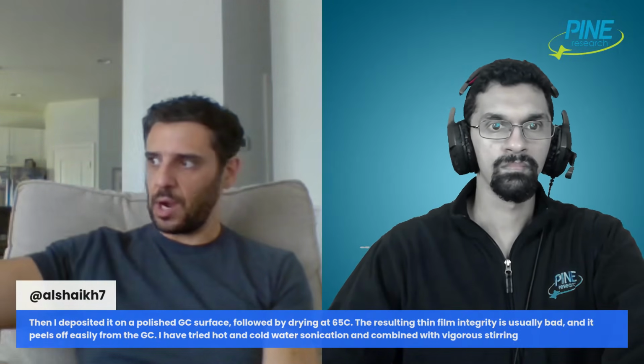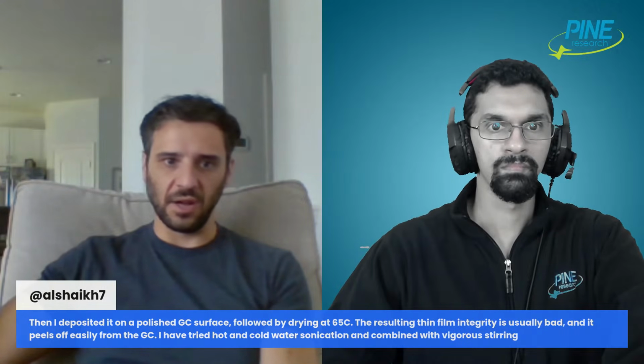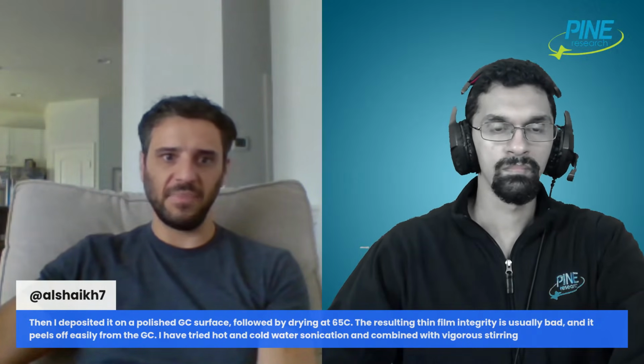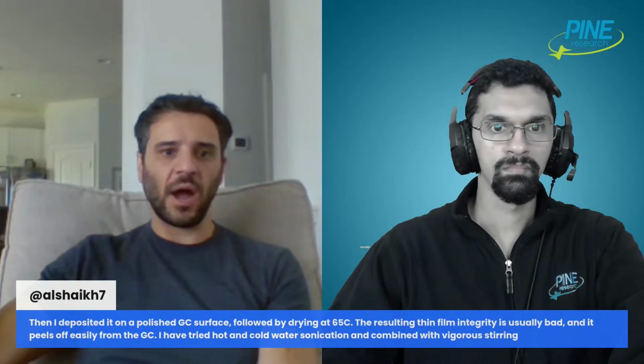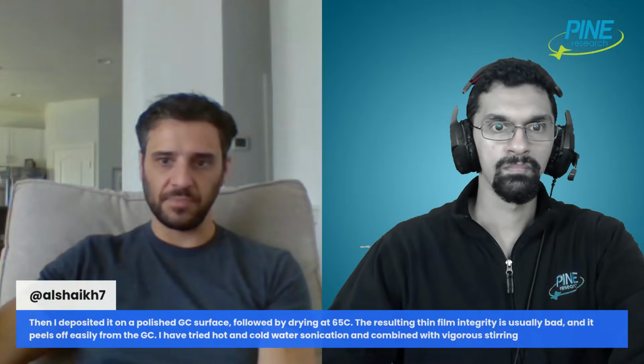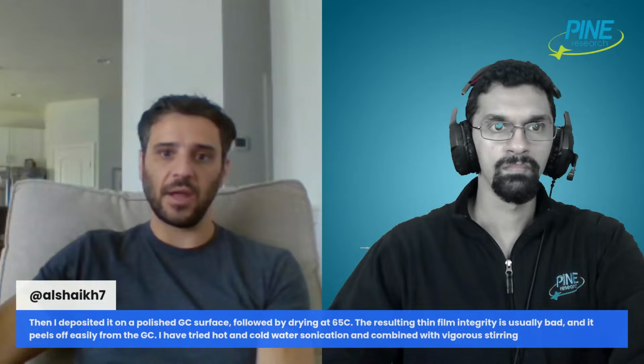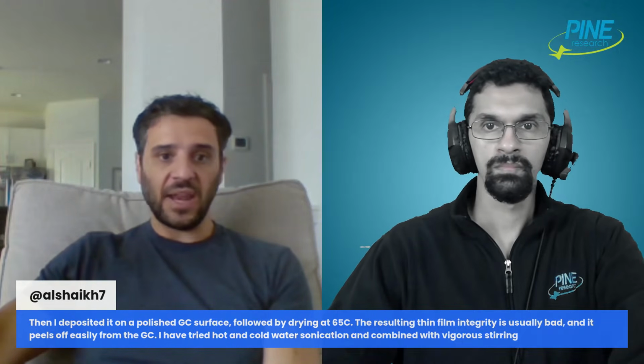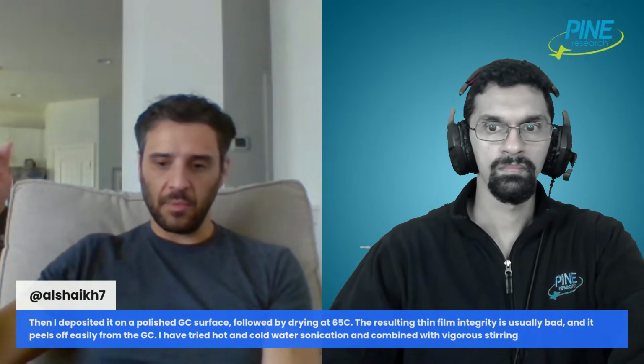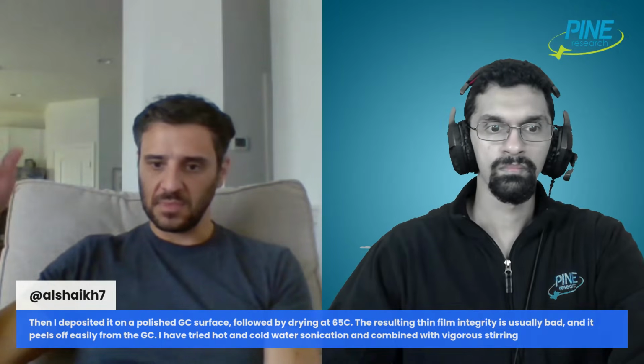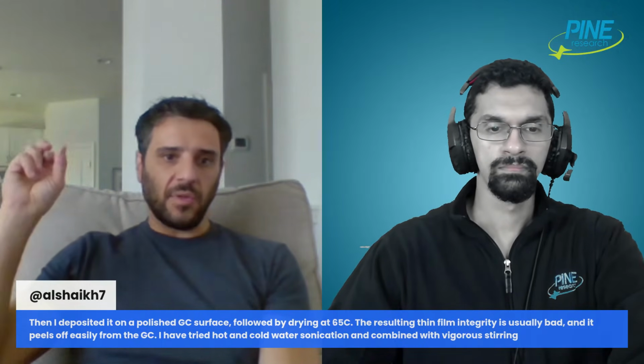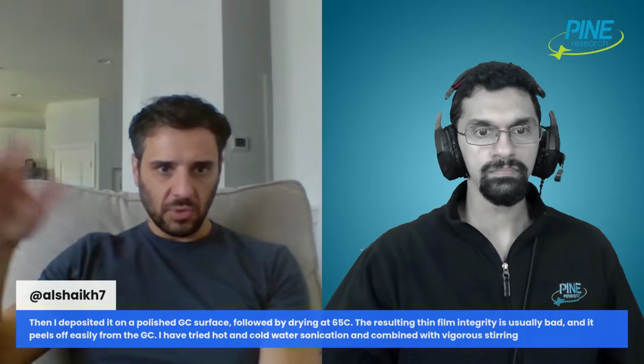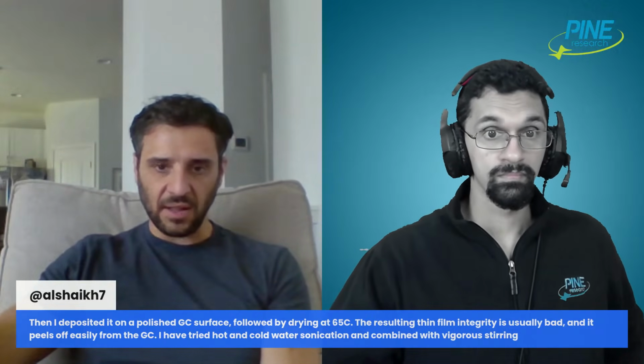Just put a droplet of ethanol on the table, see how long it takes to evaporate. It takes minutes at most. So I don't see why you really need to even use an oven in the first place. Personally, I don't think that's necessary. So dry it in air, rotate it, make it nice and uniform. And then you've just got the physisorbed, dried catalyst there.